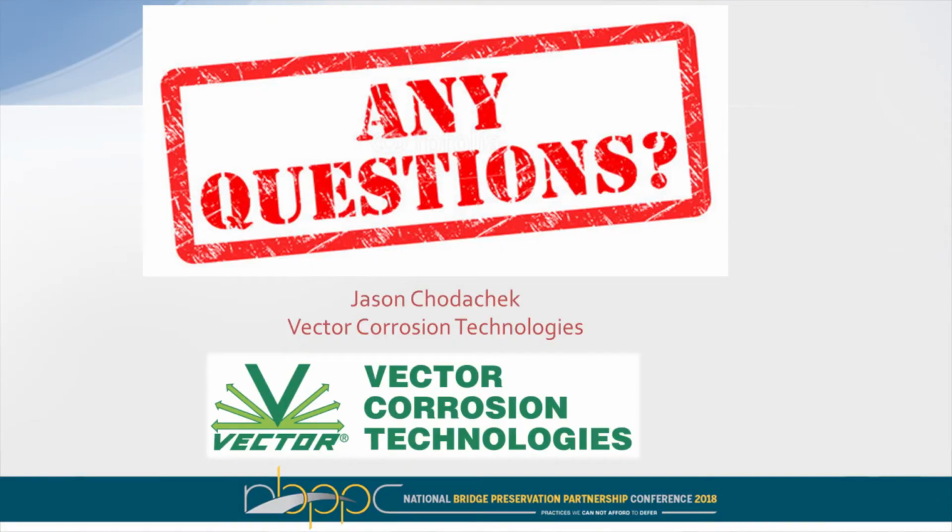What kind of lifespans are we looking for with the CP jackets? Are they different for the different types, mainly for the anodes? Yeah, so what's a typical lifespan? I think an average lifespan is around 20 years, maybe a little bit more. If you're looking to extend it further, you can add more zinc to it. Some of the systems you can do with tighter spacing. The more zinc that you add, obviously the more current that you can provide. Your structure is going to have a certain current draw, and so it's going to be designed around that.